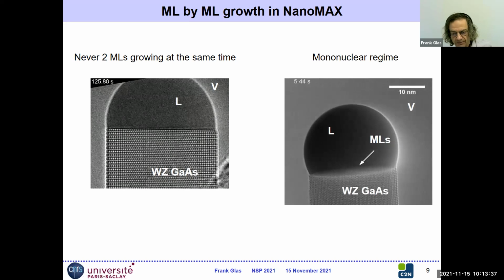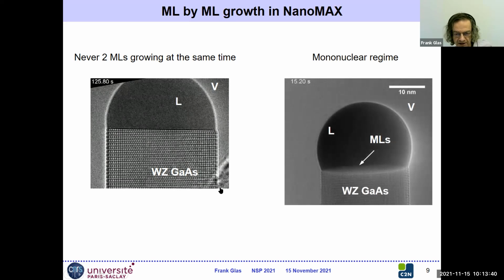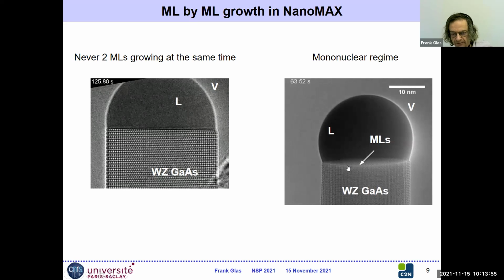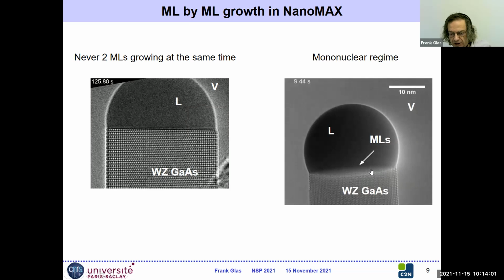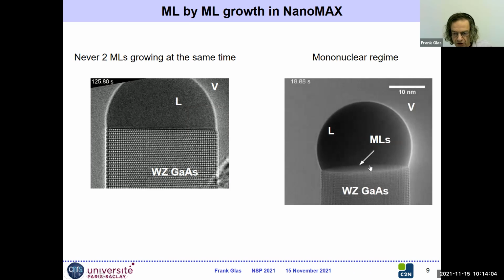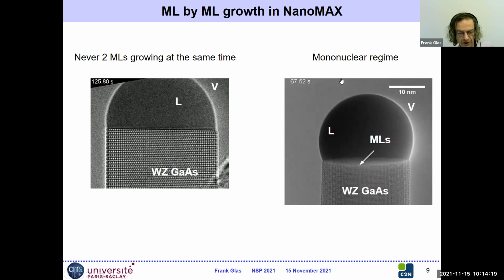Now, to get a better view, you have to tilt this nanowire so that the interface between the solid and the liquid projects as a surface. And of course, the contrast is very weak, but then you can see a kind of white shadow which is passing across this interface. This is a monolayer growing. And from this, it's very clear that we're in the mononuclear regime. Once the monolayer has started growing, then the full monolayer will grow from this nucleus, from this initial island. There will not be another monolayer which nucleates and which will meet the initial monolayer, at least in these growth conditions. So we have these two important facts that confirm our basic views about the formation of monolayers in nanowires.